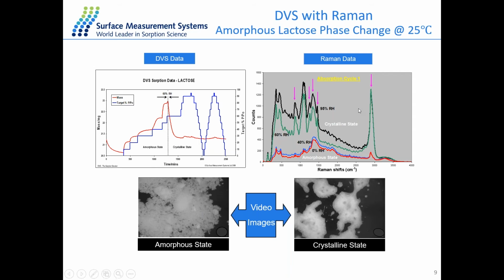And then we did the Raman spectroscopy at the end of each humidity step, so we collected the Raman spectra along with the DVS data. At 0 and 40% RH, the Raman spectra show an amorphous state. And exactly above 60% RH, some new peaks show up here, indicating the crystalline state. So this Raman data confirms our observations in the DVS data that at 60% RH, this amorphous lactose sample goes through the amorphous to crystalline phase change. You can see the same in the video images as well. The combination of video images, Raman spectra, and the DVS technique can give a very good understanding of solid characterization for different kinds of samples.